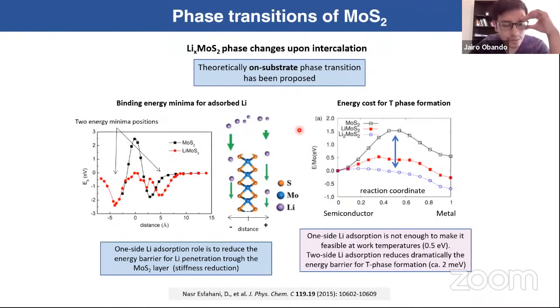So as I was telling Juan, the intercalation can happen whether you're using basal planes or stepped surfaces, because when you put lithium, this helps at the very first to form a top layer on the surface, and this layer lowers the potential barrier for lithium to overcome through the structure. This has to do with the stiffness of the structure, and this is why the intercalation can happen at first with a basal oriented sample, through the structure and also through sulfur defects. And when you're using stepped oriented surfaces, the intercalation takes place through the interlayer space. Thank you, Jairo. Any question?